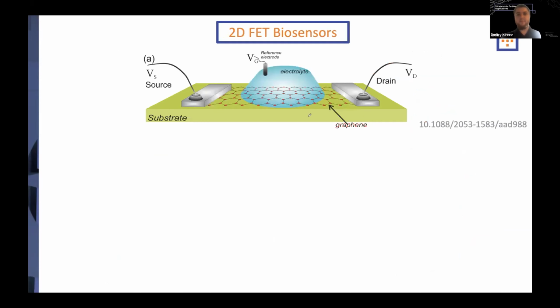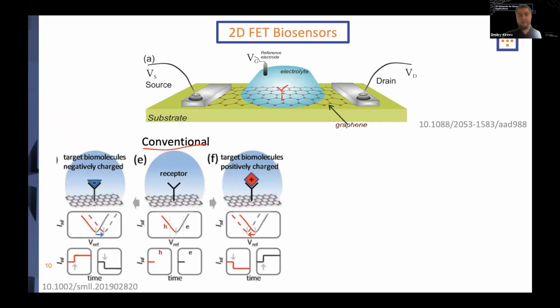So this is a schematic of a biosensor. You have a source and drain, you have electrolyte, and you have a liquid on top of it with functionalized receptors. So a conventional biosensing would be, you start with a receptor on top of a graphene surface, and you measure the performance of the device. You have this typical V-shaped IV curve. And then once a charged molecule comes in contact with the receptor, so let's say if it's a positively charged molecule, an extra positive charge comes to the receptor, you receive a left shift of the Dirac point, and you have a drop in the current. If an oppositely charged, negatively charged molecule comes to the receptor, you have a right shift of the voltage, or an increase of the current. So that is really conventional biosensing.